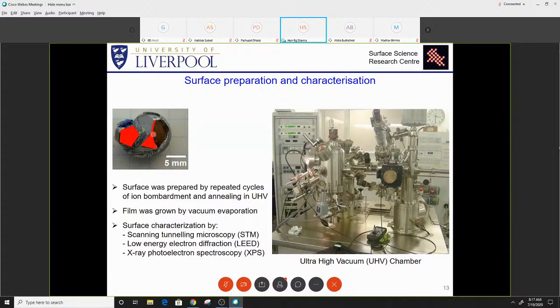an ultra high vacuum chamber, sputter it with ion bombardment several times. Once we think the sample is ready, we transfer it to the characterization chamber. We use various experimental techniques to characterize it, like scanning tunneling microscopy for structural characterization. For chemical characterization, we have to use another technique. Once the characterized surface is ready, then